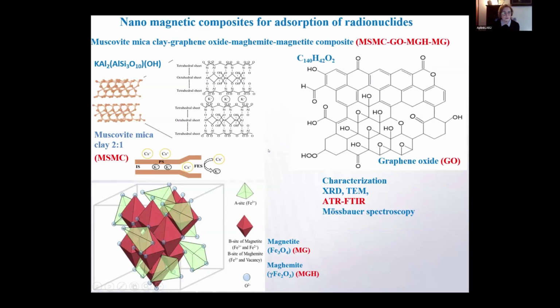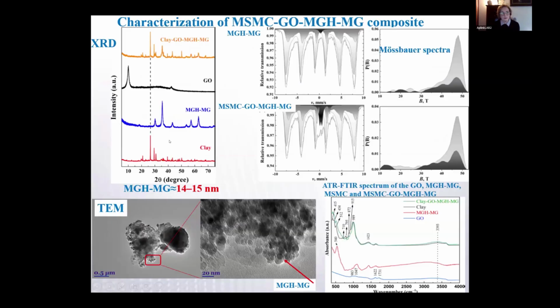So I'll start with composites that contained mica clay of local origin. It was synthesized using muscovite, graphene oxide, and magnetite and maghemite nanoparticles. Characterization was performed using XRD and Mössbauer spectroscopy, and in the samples we found nanoparticles of magnetite and maghemite of 14-15 nanometers, and spectroscopic analysis indicated various functional groups available for adsorption.